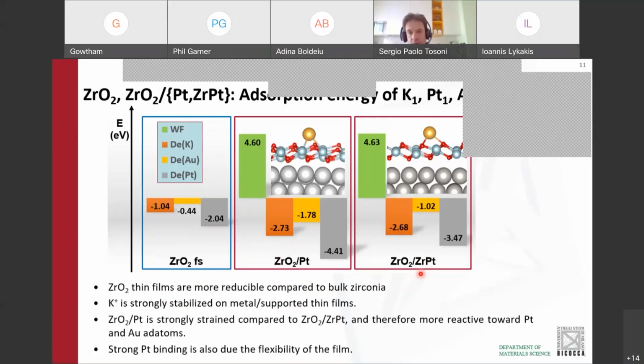the zirconium platinum alloy. This is due to the large strain that the film undergoes in the ZrO2/Pt system compared to the Zr-Pt support. And this makes the film more reactive, and therefore the adsorption energy of all atomic species is larger. And the film is very flexible. When you put platinum on top of it, there is a strong local rearrangement of the film, which permits to bind very strongly the platinum atom, as you can see. The same takes place also on freestanding zirconia.